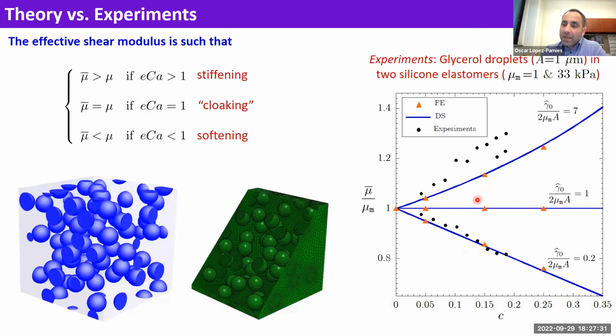Cloaking means that you may have a system where, even though you have inclusions, you have neither softening nor stiffening, but it would behave exactly as the matrix without the inclusions, even though the inclusions are being deformed. So what this is telling you is that you can actually cover a wide range of behaviors, from softening to stiffening to cloaking, by playing around with liquid inclusions, their sizes, and their interfaces.